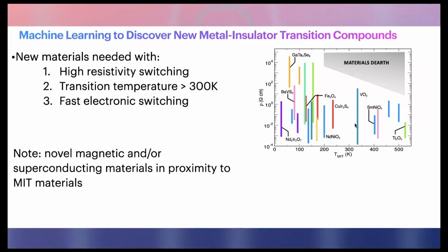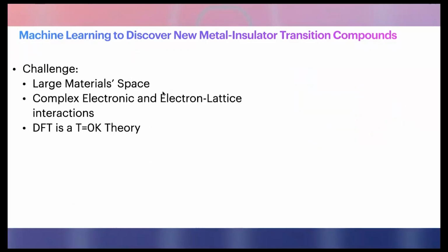As much as I like samarium nickelate and neodymium nickelate, neodymium nickelate is under 300 and samarium nickelate isn't as sharp. And actually, with the nickelates, the further you go in temperature, the less sharp the transition is. So yeah, you have a challenge then, you have a large material space.